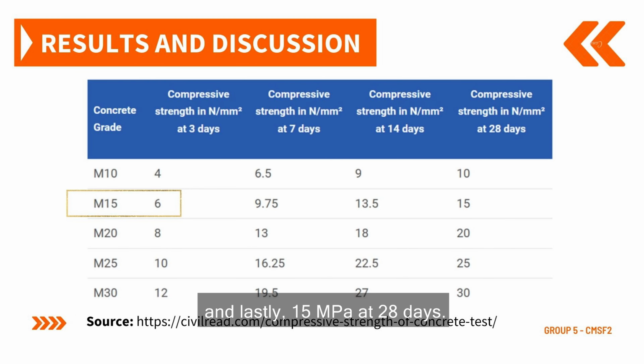Next, we have here a table containing the standard specifications for the compressive strength of cylindrical concrete specimens. For Class A mixture or the 1:2:4 cement, sand, coarse aggregate ratio, this falls under concrete grade M15. This grade has a minimum compressive strength requirement of 6 megapascals at 3 days, 9.75 megapascals at 7 days, 13.5 megapascals at 14 days, and lastly, 15 megapascals at 28 days.